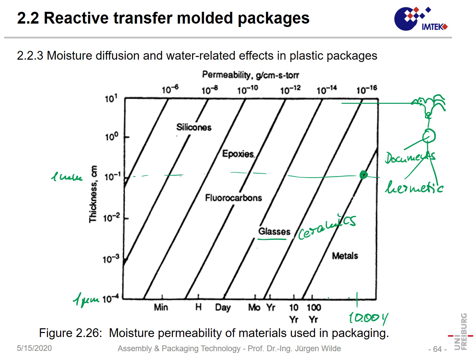The best polymers still are fluorocarbons, like for instance PTFE, Teflon, which are still quite good, but epoxies are worse. So in epoxies we already have diffusion, and when we look at, for instance, 1 millimeter, that would mean moisture penetrates epoxies within minutes to hours.